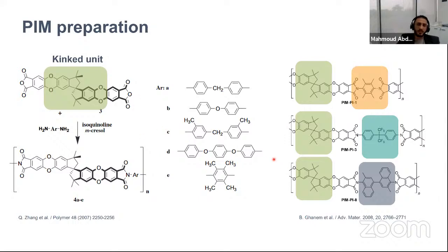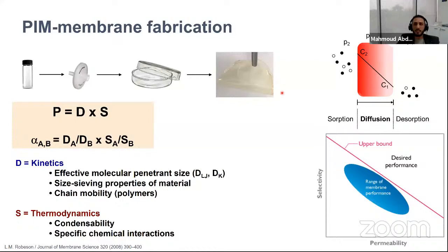Once you have this polymer, there is a protocol to follow to prepare a membrane for gas separation. First, it starts with dissolving your polymer in a proper solvent like chloroform or dichloromethane, or even polar aprotic solvents such as DMF or NMP. Then you filter your polymer and cast it in a flat Petri dish and let it evaporate at a specific temperature, maybe room temperature, or you may need to heat a little to remove the solvent. You end up having this kind of membrane. This is known as a dense membrane, with a thickness usually ranging between 30, 40 up to 100 micrometers.